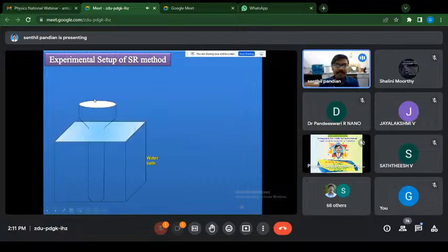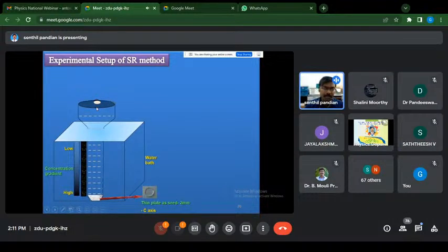So the experimental setup of this SR method consists of the glass sample, and this SR glass sample is kept inside this water bath, and a small thin plate like a seed crystal is mounted at the bottom of the glass sample. Then we pour the saturated solution inside this glass sample, and a small hole is made on the top of the glass sample for solvent evaporation. After a few hours, due to gravity driven concentration, all the solute molecules approach the crystal surface directly. So the crystal surface attracts more atoms very easily. Because of the gravity driven concentration, at the bottom portion near the seed crystal and solution interface, the concentration is high compared to the top portion.